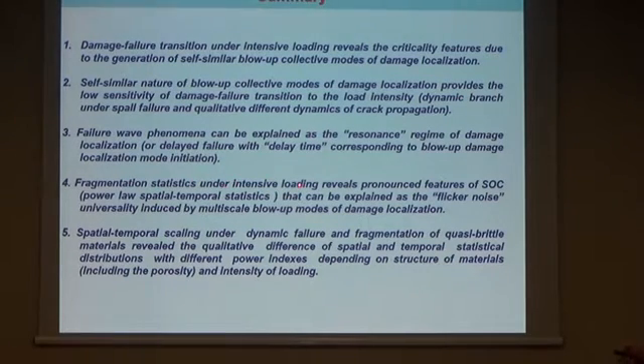Fragmentation statistics under intensive loading reveal pronounced features of self-organized criticality, power law, and special temporal statistics that can be explained as a flicker noise universality caused by multi-scale blow-up modes of damage localization. And special temporal scaling under dynamic failure and fragmentation of quasi-brittle material reveals the qualitative difference of statistical distribution with different power indexes depending on the structure of the material, including porosity and intensity of the loading.